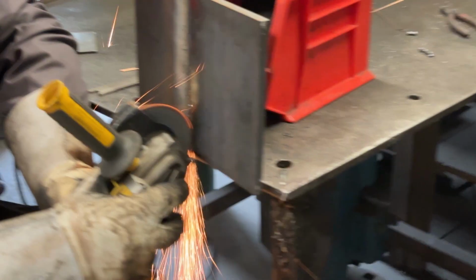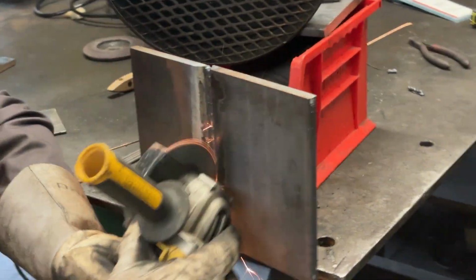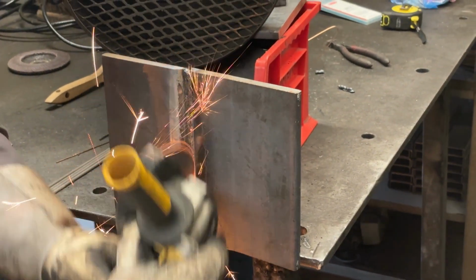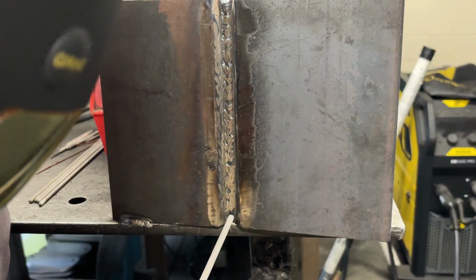To avoid this, we need to control our arc length, travel speed and rod angle carefully. We do this by adding a slight weave to our run, keeping a steady hand and consistent movement. This will help us build up the weld without disturbing or overheating the root run. With that run complete, we deslag the weld and then use the grinder again to make sure all traces of that slag are removed. Once everything is cleaned up, we move on to our third pass.